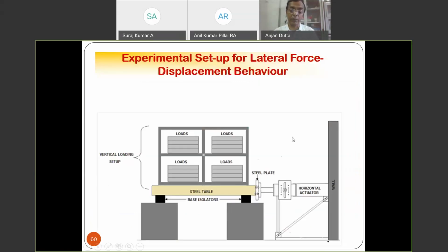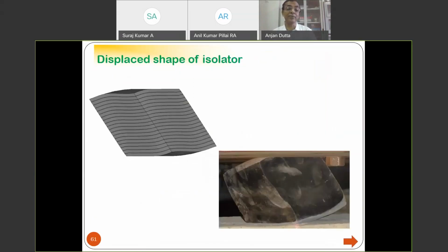We have carried out detailed experimental investigation for this kind of isolator to find out those characteristics, because numerically, eventually after you have manufactured, and this is a requirement for base isolated buildings, every isolator needs to be tested. So we have tested them, and you can see now this is what we have got. In the numerical simulation, there is a step rollover deformation, and you can see the rollover deformation here also. And this is actually not connected, they are only in contact with the substructure and superstructure. Load displacement and numerical, they are more or less a very good match, you can see.